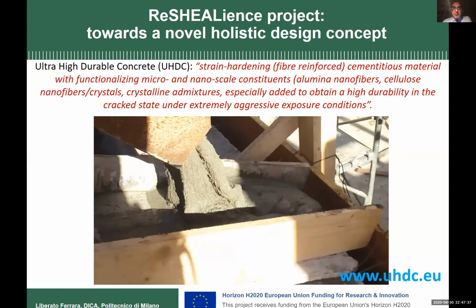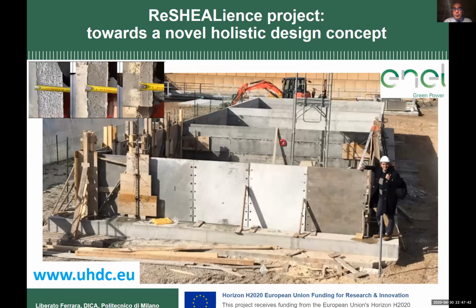This is the pilot built, and you can see me on the corner. It's 20 meters long by about 7 meters wide. On the bottom you can see the original solution, in the middle the 6-centimeter thick solution, and this is the precast - you can see the slabs and some of the formworks for the columns. In these insets on the top left, you see the 10-centimeter original reinforced concrete wall, the 6-centimeter thick UHDC, and the 3-centimeter thick, just to show you these are not numbers, this is reality.